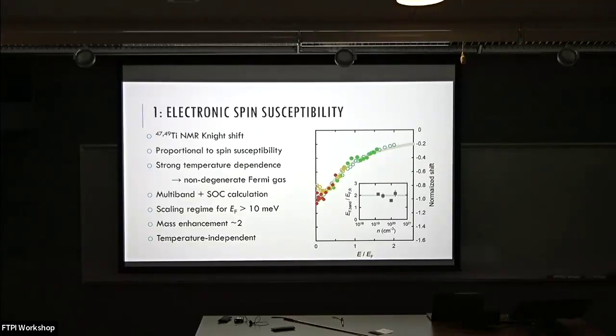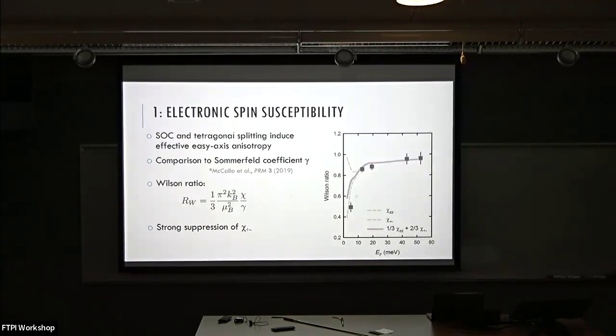But there is another interesting effect, which we only recently realized exists. And this is that if you combine this spin-orbit coupling and tetragonal splitting, there is an effective easy axis anisotropy. So in the low doping limit, you can do a comparison to the Sommerfeld coefficient, which was measured previously by Chris's group here, through something called the Wilson ratio. So you can do susceptibility divided by gamma. There's a pre-factor that makes this 1 for free electrons. But then what we see in experiment is that it falls below 1, significantly below 1. And you can actually reproduce this with this band computation, and you get this strong anisotropy. So basically the longitudinal susceptibility is nearly 1. There's a little minimum here, but the transverse goes down strongly. So basically a combination of these two creates an easy axis.